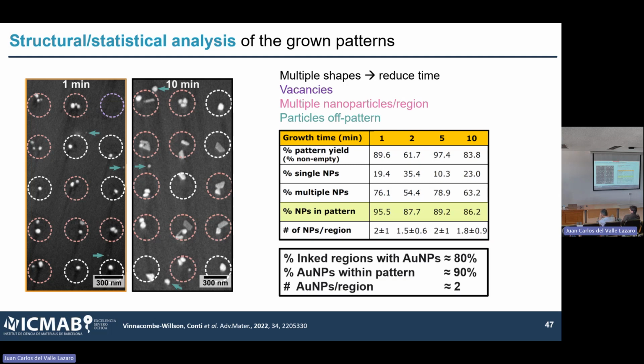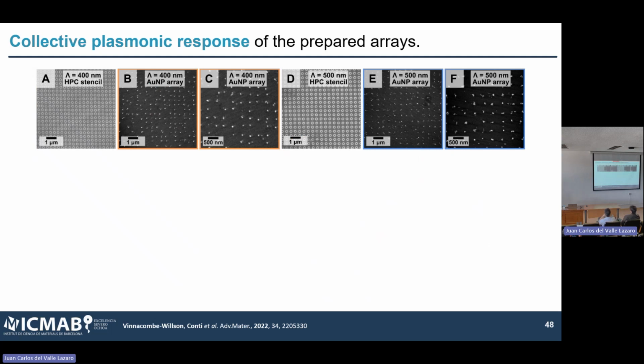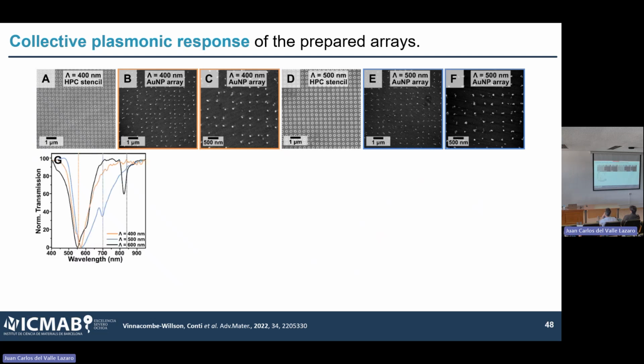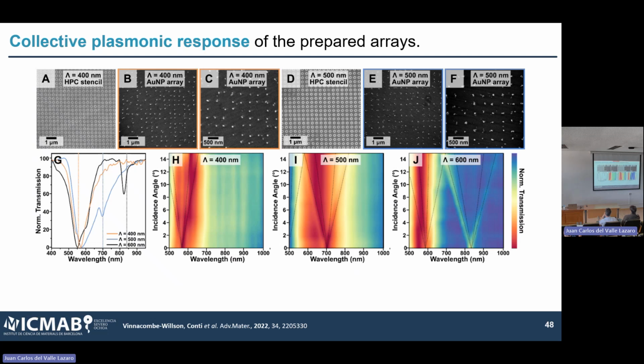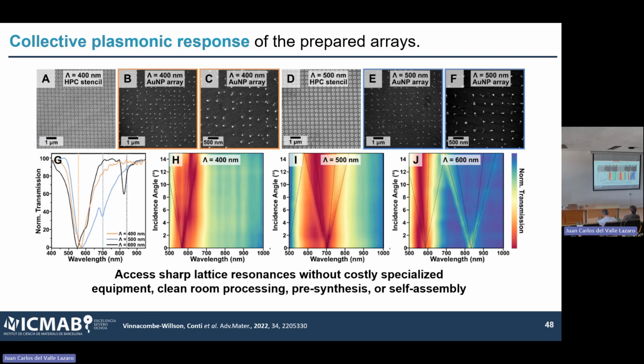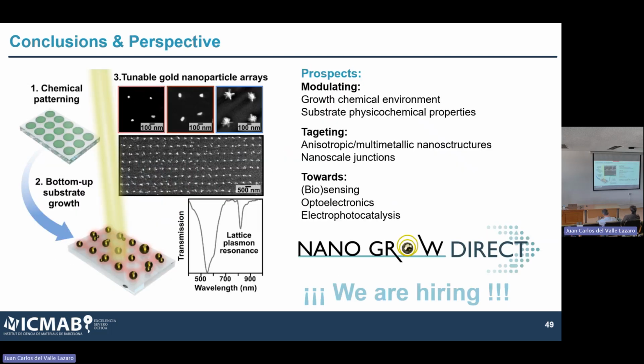Okay, so finally, this is something that is important because I told you the whole story telling you that we can make metasurfaces. So are these metasurfaces? To do that, we did our standard optical characterization, and indeed we see the presence of a lattice resonance. I was very surprised because the system is not extremely perfect, so the defects in the system will have a detrimental effect on your collective response. But indeed, we were able to observe these lattice resonances and see how they change with the angle, as I showed you for the previous project. So yes, we were able to access sharp lattice resonances for a system that was completely grown in situ. And so we are really excited about this.